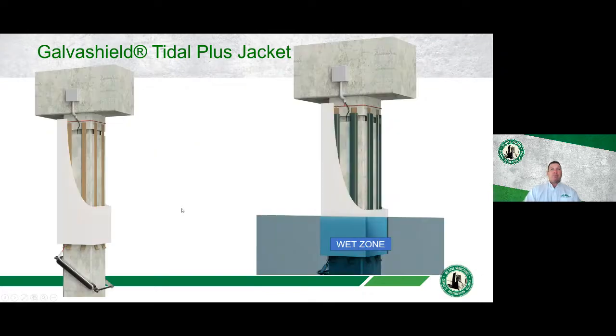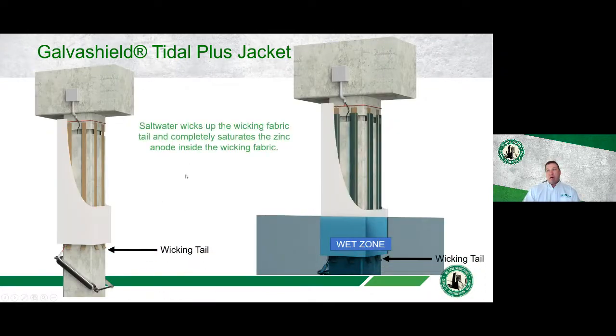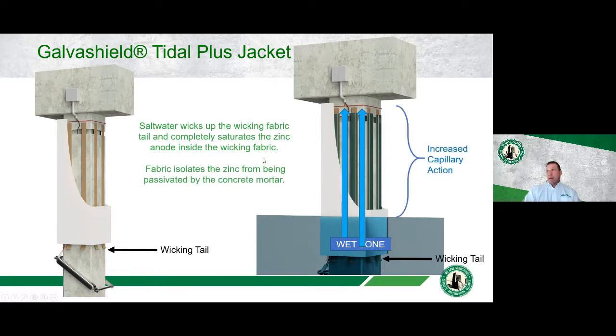So here again is just a depiction of how the system works. We have our wicking tails that are extending out the bottom of the jacket. And if you look over here on the right, this is our wet zone. So we have our wicking tail. The water actually works its way up this wicking fabric and encompasses the entire anode within that fabric. So we end up getting very, very good wetting. We end up getting a lot more current out of it because of this increased capillary action.